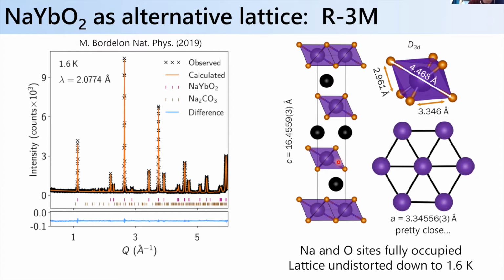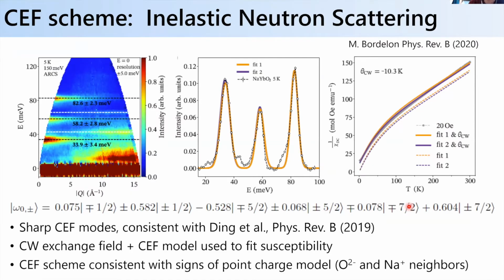Okay, and so another fact that we can get from the neutron scattering data that I've shown you here is that the actual distance between the ytterbium ions within the triangular lattice is about 3.34 angstroms, which is pretty close for a number of rare earth oxides, especially ytterbium systems. I think this is sort of the closest ytterbium distance that we were able to dig up. I'm sure there's an exception, but it's close relative to some of the more well-studied materials. And the reason that's important is that means we should expect a reasonably enhanced magnetic exchange parameter along that exchange pathway.